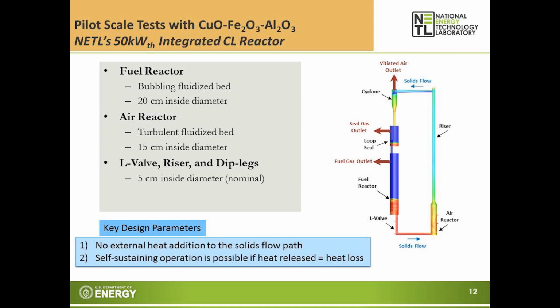So we tested this material, the copper and alumina oxygen carrier, in our 50 kilowatt thermal integrated chemical looping reactor. And the fuel reactor here is a bubbling fluidized bed. We introduced methane here. And after that, it's transported to the air reactor using an L-valve. In the air reactor, we introduce air, and it's transferred through the riser to the cyclone and back to the fuel reactor. And the air reactor is a turbulent fluidized bed. So some of the key design parameters: there's no external heat added to the solid paths. So self-sustaining operation is possible if heat released is equal to the heat loss.